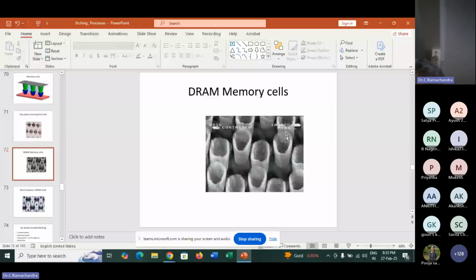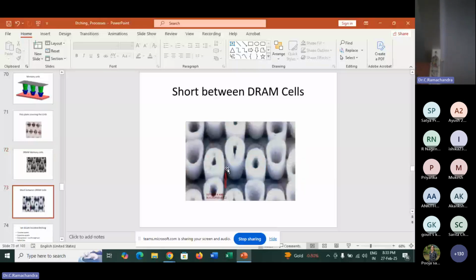This is only a small part I am seeing. Throughout the wafer, there are 512 million of this kind of cells. Now we have taken a failed sample where we had a signature which is suspected to be memory cell-to-cell short, and we did the same process, and we identified it. You can see short between cell-to-cell after etching, so we could confirm. So this technology, both detection of IBC and detection of cell-to-cell short, was a very, very wonderful experiment and project for us. We were successful. Those days, these are all the work done in 99.